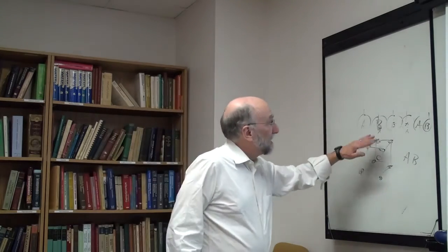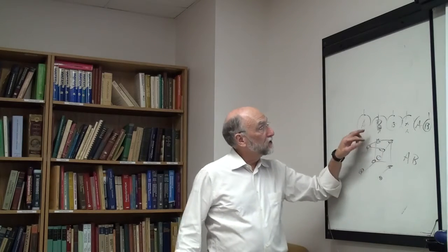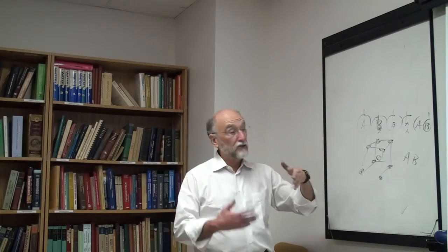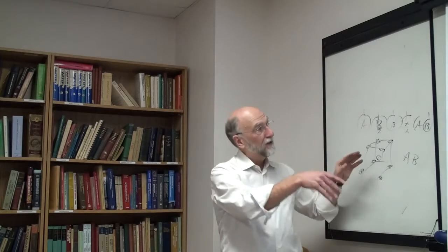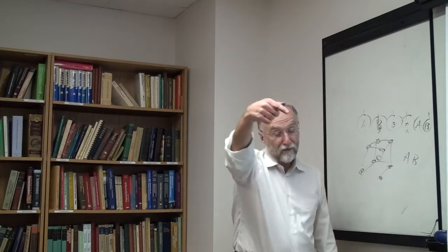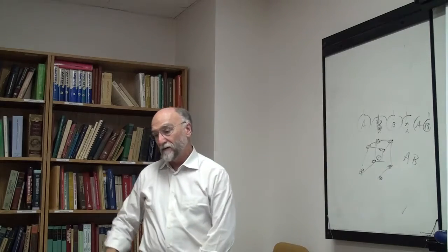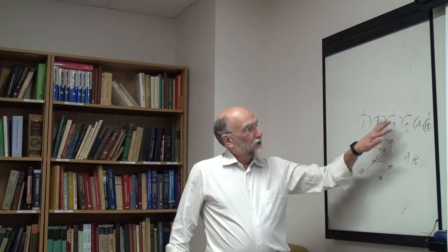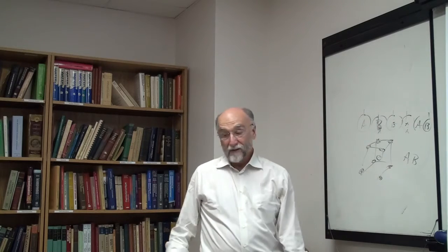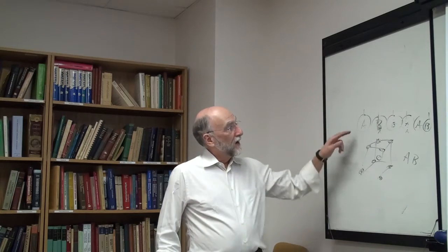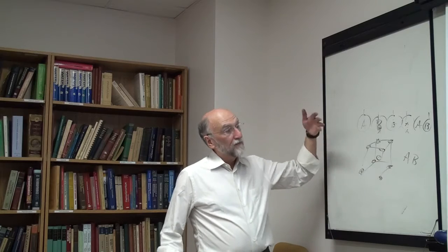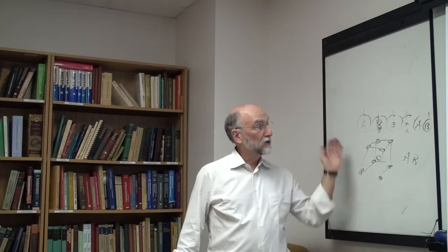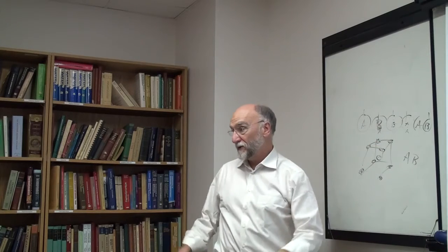So here you can have a lattice that at first glance, this is long range order, but with a very high substitutional disorder. So when you look at it, it looks almost disordered, A, B, B, A, B, B. And yet the probability, no matter how far you go, is still greater than 50% that there's long range order. So here you have a lattice that looks disordered, but even at long distances, it's ordered. On the other hand, as I said, you could have 99.9% short range order, A, B, A, B, A, B, so it looks perfectly ordered, but at long distances it's completely disordered.